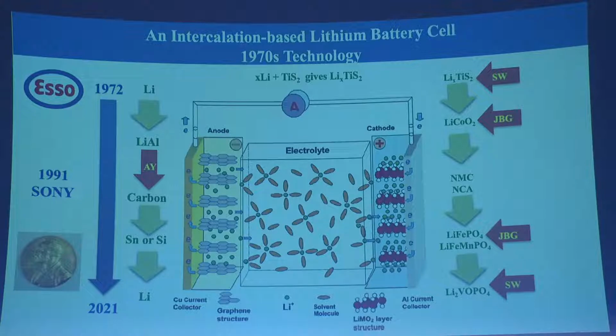The superconductivity materials were tantalum disulfide, very heavy. Somebody was asking about what you can intercalate in these materials. We were looking at long chain amines, C24, then the amine group at the end of it. So we could spread the layers apart, change the electron density, and that changed their superconductivity. As soon as we got interested in the energy, we switched from tantalum to titanium for obvious reasons. Much lighter. Now, I'll show you in a minute, titanium has some other big positive parameters.